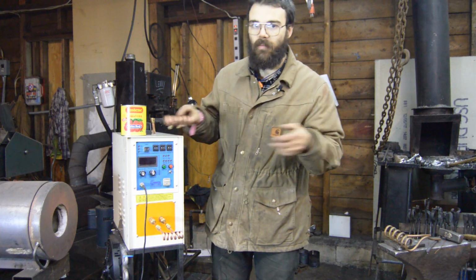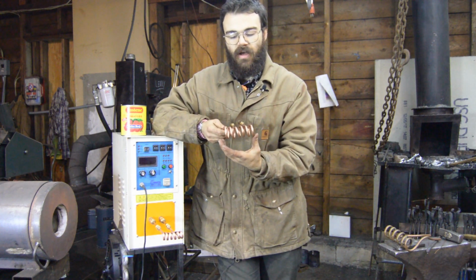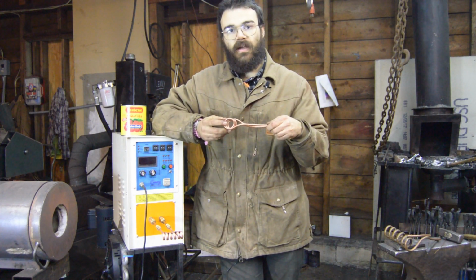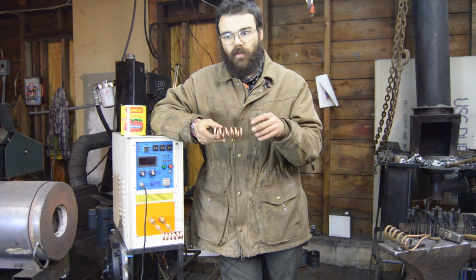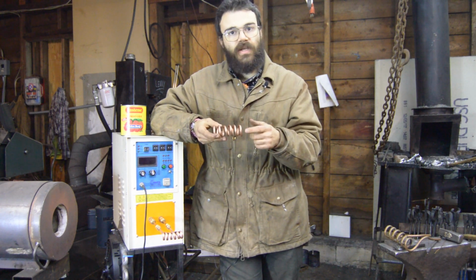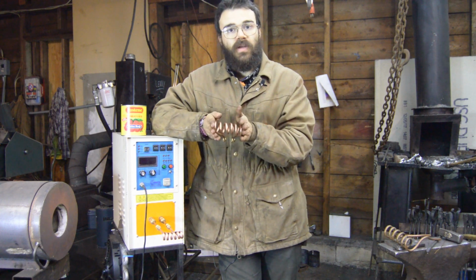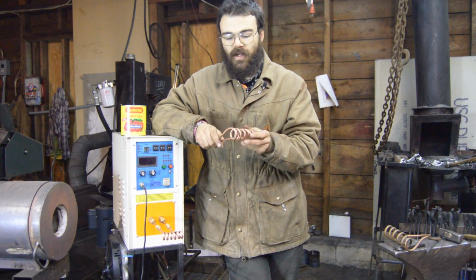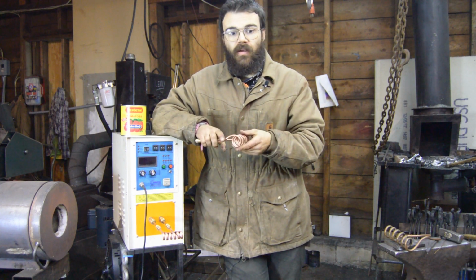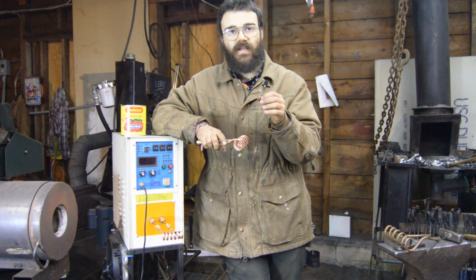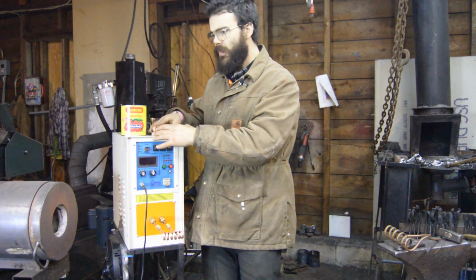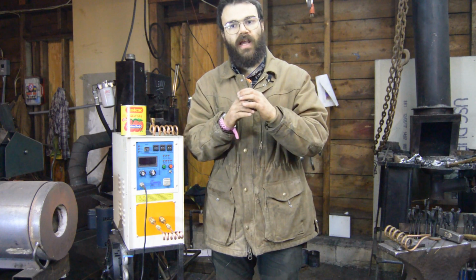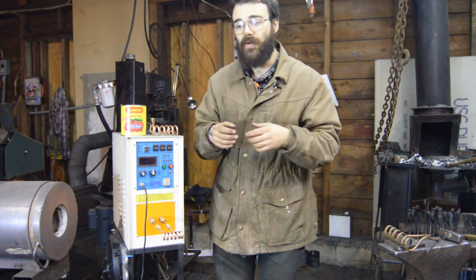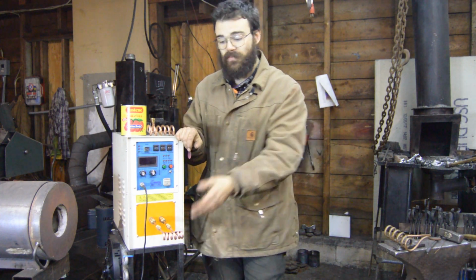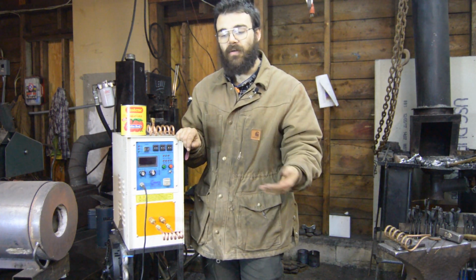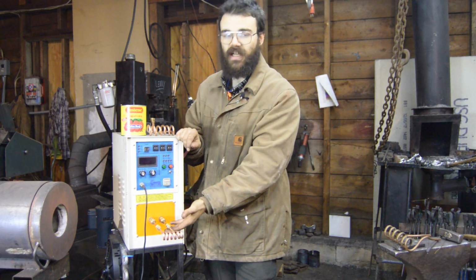The last thing, and probably the most important, is the ratio of the length of your coil to its inner diameter. For multi-turn coils, you want to keep it within about 4 to 1. So if you have a 1-inch inner diameter of your coil, you want to keep it 4 inches long or shorter, if at all possible. This basically has to do with how concentrated the magnetic field lines can get inside the toroid. Once you get a 4 to 1 ratio, those magnetic field lines will have been concentrated and will be about as linear as they're ever going to get. So adding more tubing after that only increases the resistivity of the coil, and therefore you're taking power away from the induction part of the heating, and you're just heating up the coil because it's turning into a bigger and bigger resistor.